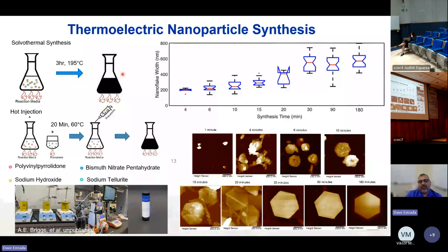We've since taken the solvothermal method and improved it through a hot injection method, where we separate the precursors from the reaction media, heat them separately at 60 degrees Celsius, and use a syringe pump to have more control over the reaction. And so what we did here is just a time series of AFM images where we stopped the reaction at 1 minute, 4, 6, 10, 15, 20, et cetera. And what we found is that at 20 minutes, we actually get nice crystalline domains of these thermoelectric nanoplatelets.